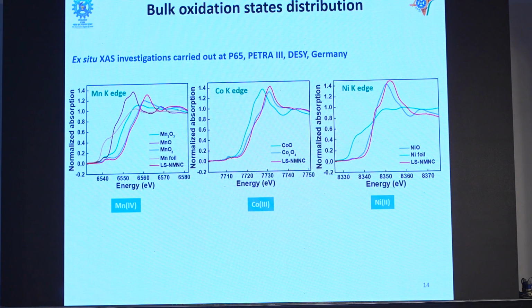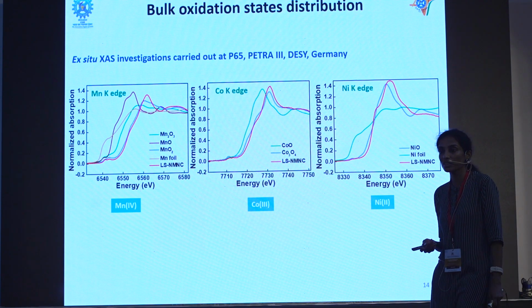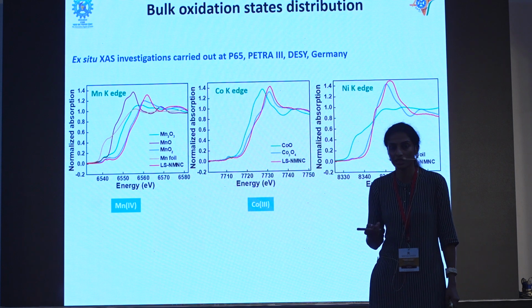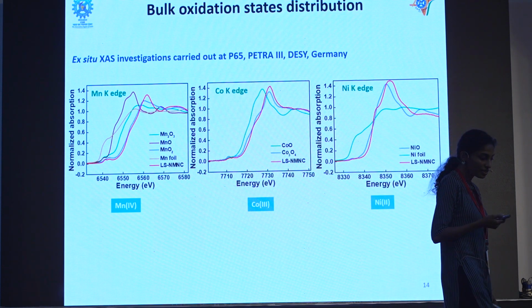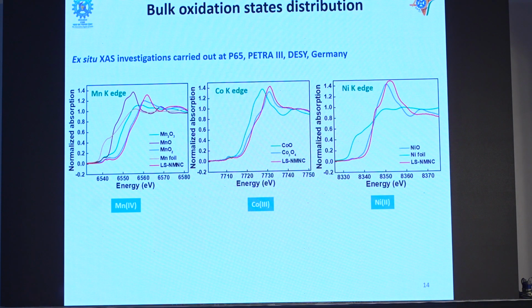The next thing, we analyzed it using ICP-OES just to fix the composition, and it was very close to the composition. So next, the challenge was to understand the oxidation state distribution of the different cations in the material. So we used X-ray absorption spectroscopy in collaboration with Petra.